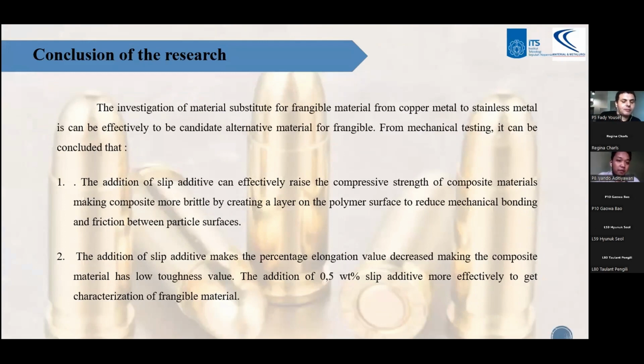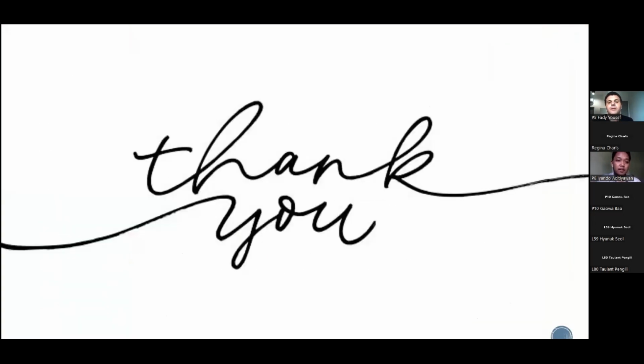And the conclusion of the research: the investigation of metal substitution for frangible material from copper metal to stainless steel shows it can effectively be a candidate alternative material for frangible bullets. From mechanical testing, it can be concluded that the addition of slip additive can effectively raise the compressive strength of the composite material, making the composite more brittle by creating a layer on the polymer surface to reduce mechanical bonding and friction between particle surfaces. The addition of slip additive makes the percentage elongation value decrease, making the composite material have a low toughness value. The addition of 0.5 weight percent slip additive is more effective for characterization of frangible material. This is my reference, and thank you for your attention.